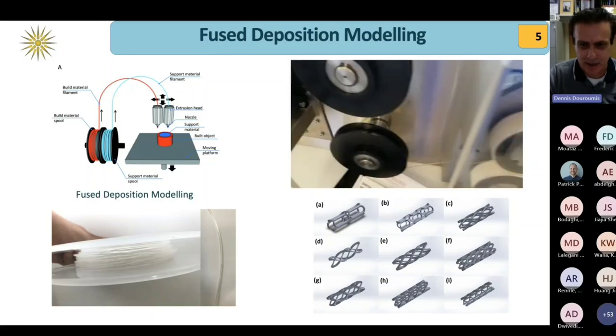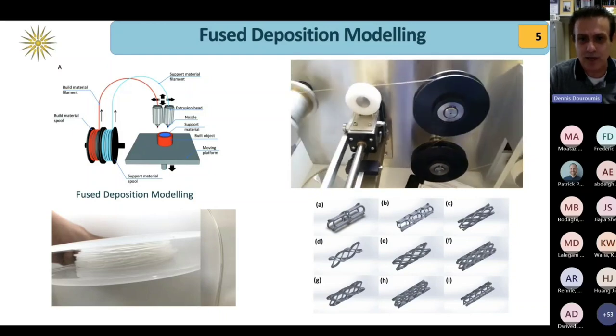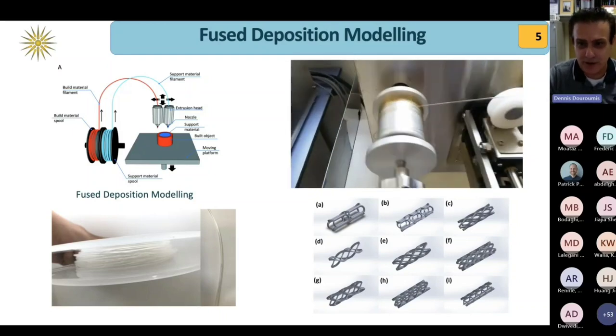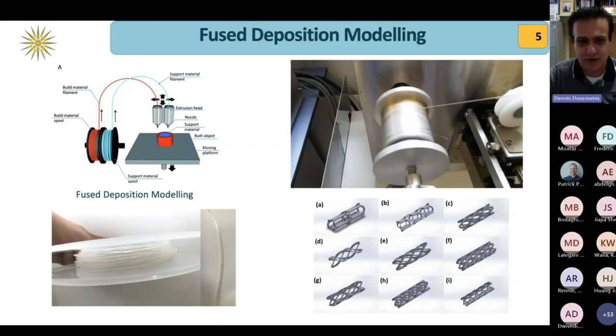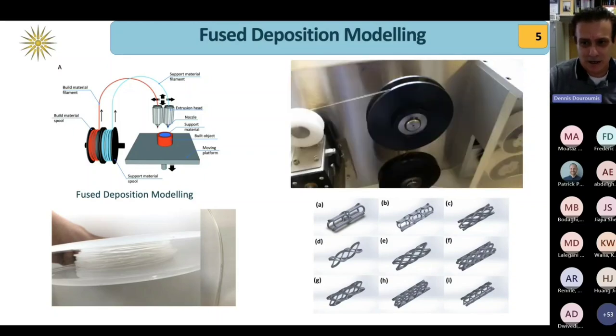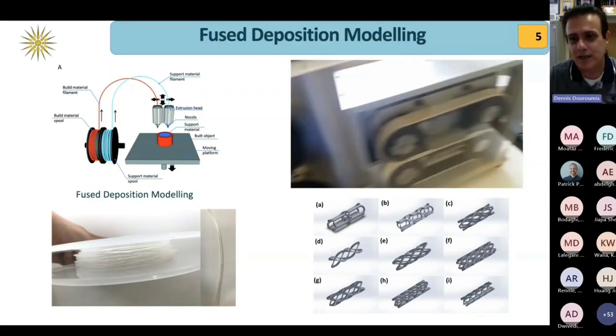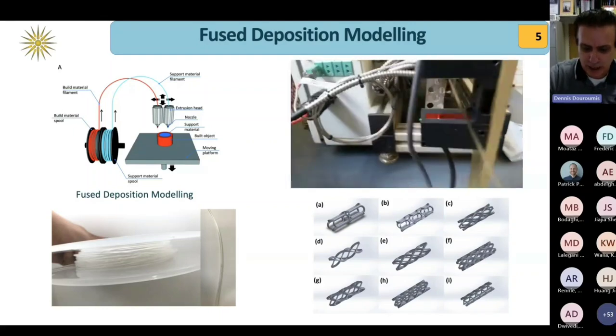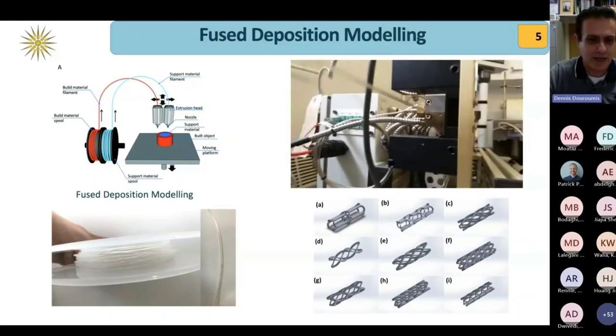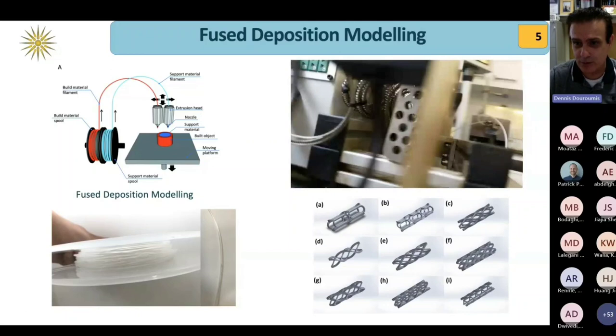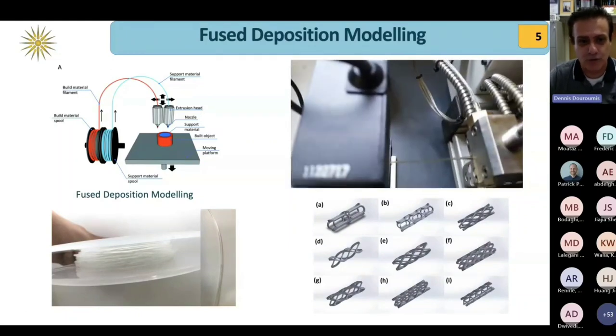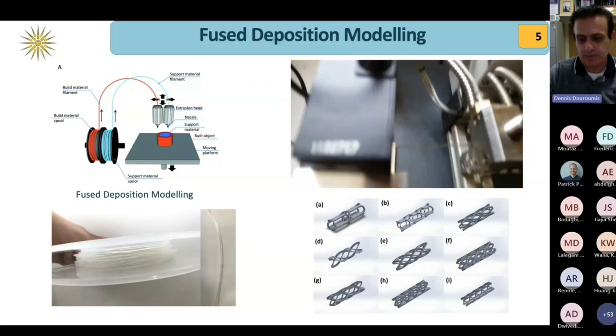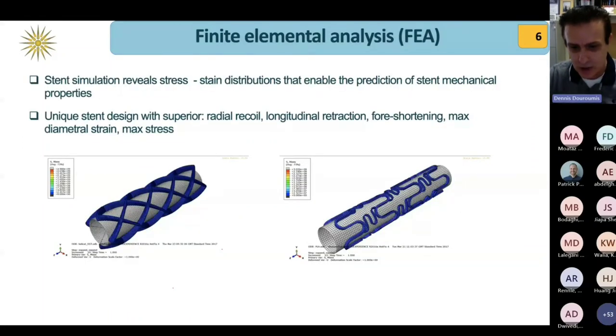We can collect the filament. This could be an empty filament, or a drug-loaded filament, so there are a lot of different options. After the collection of the filament, a process which is highly accurate to avoid any defects during 3D printing, we could use our polymers. Also, the idea was that we can use a combination of polymers by optimizing extrusion in order to improve mechanical properties. Before that, of course, we waste a lot of material because in order to process with one of these extruders, we need at least 20 grams per material, and the polymers can be quite expensive.